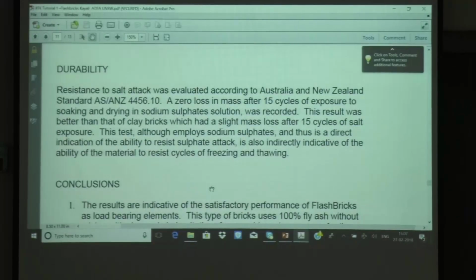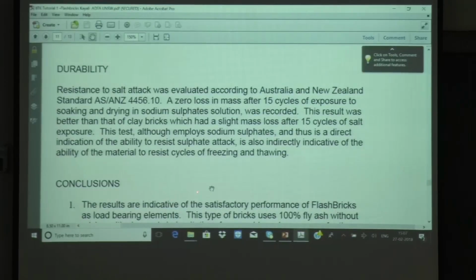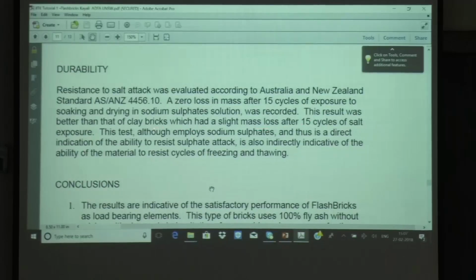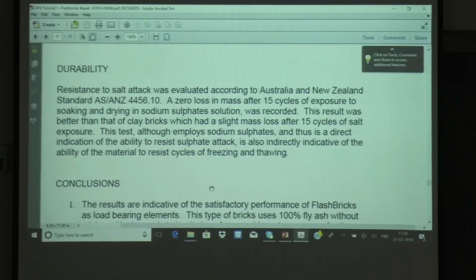The durability is the final part of this investigation. Resistance to salt attack was evaluated according to the Australian and New Zealand standard. A zero loss in mass after 15 cycles of exposure to soaking and drying was recorded. So there is zero loss of mass. This is very good, because this result was much better than the clay bricks, which had a slight mass loss after 15 cycles of salt exposure.